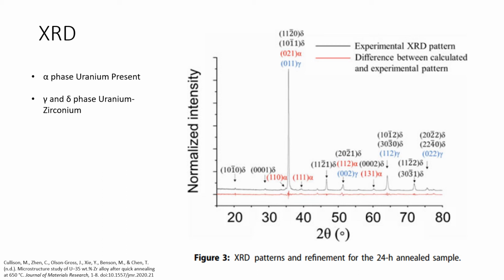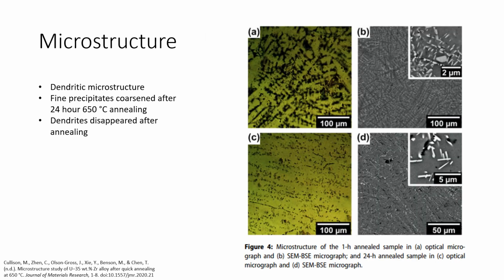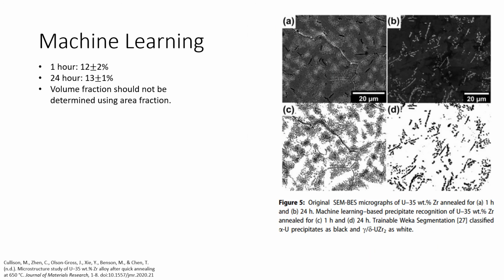We found the matrix was a mix of delta and gamma phase uranium zirconium alloy, while the precipitates were alpha phase uranium. The electron micrographs revealed a dendritic, or tree-like, structure in the matrix. Annealing for 1 hour at 650 degrees Celsius revealed that there were fine precipitates, but after annealing for 24 hours, the precipitates coarsened and the dendritic microstructure disappeared.